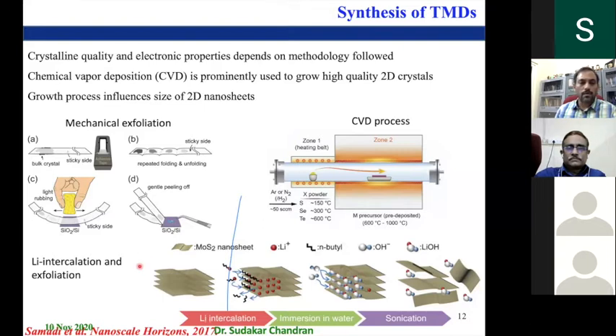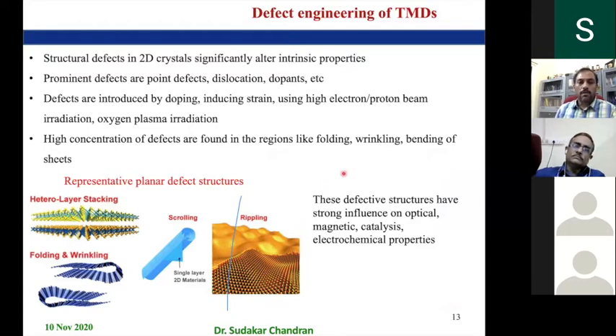The other way of doing it is you take the bulk material and intercalate certain alkali metals like lithium, and when the lithium gets into the interlayers, by dissolving and then sonicating it, you can separate all these crystals, and then you can have it in a dispersed solution, or you can transfer it onto the substrate. So these are all the ways. There are many other physical vapor depositions and chemical vapor depositions being explored to grow large area single layer crystals.